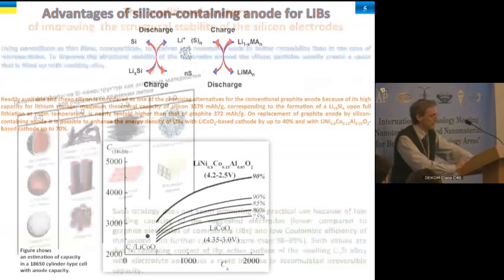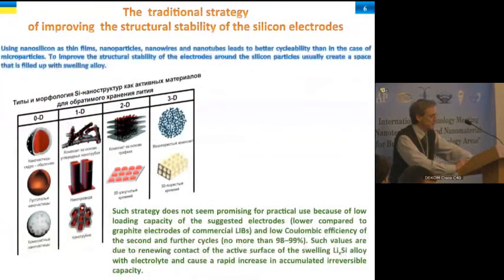To improve the structural stability of the electrodes, around the silicon particles one usually creates a space that is filled up with swelling alloy. Such a strategy does not seem promising for practical use because of low loading capacity of the suggested electrodes and low Coulombic efficiencies of the cycles due to renewing contact of the active surface of the swelling lithium silicon alloy with electrolyte.